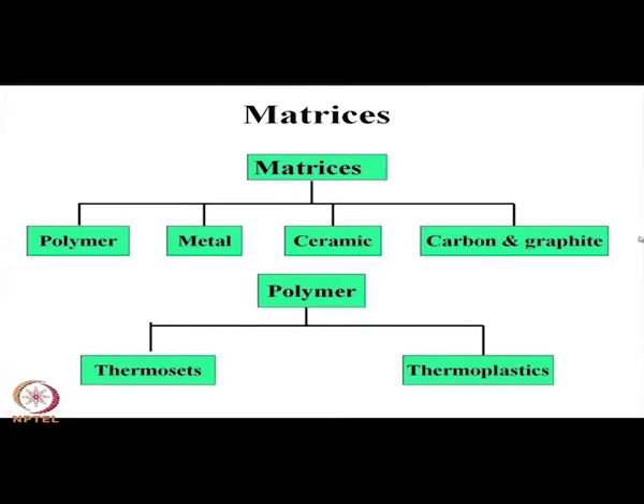Now, this carbon and graphite matrix composites can go to that extent where this carbon matrix or graphite matrix does not decompose. In fact, such a matrix is prepared by taking a porous carbon precursor, into which carbonaceous fluid is impregnated, then it is pyrolyzed in inert atmosphere, where this carbon or graphite formation occurs and it becomes a good and strong matrix, and which can stand